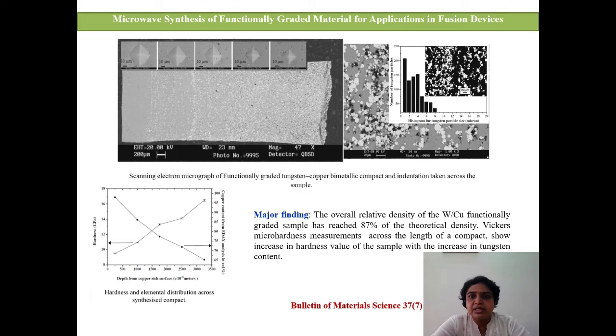In the conventional method, what is the problem? Since copper has a low melting point, it forms an elephant foot kind of flaw. Using microwave, immediate arrest can be achieved. Once you switch off the microwave power, melting can be stopped immediately. We characterized this sample with the help of hardness and density measurements.